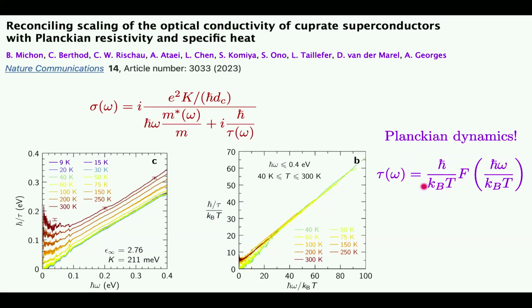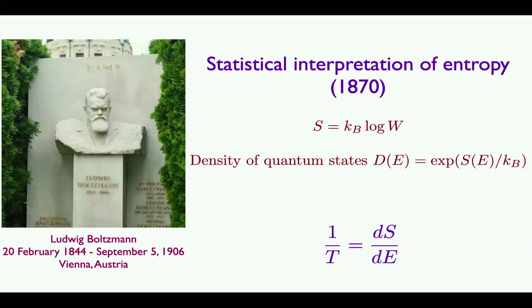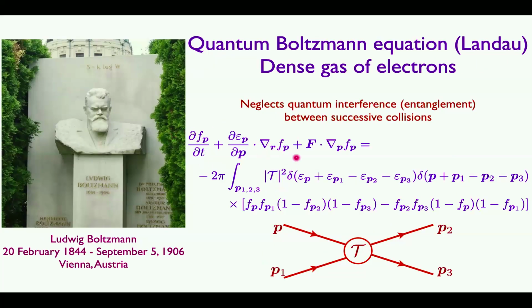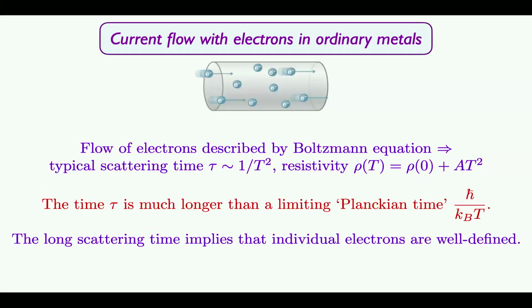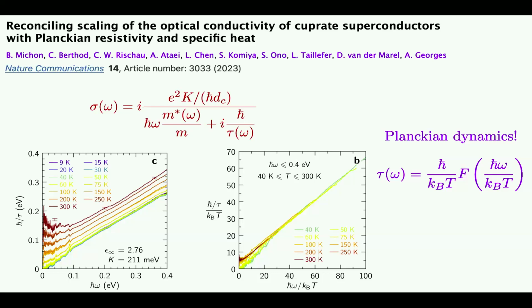And this is quite remarkable because the strength of the interaction, the fact that the repulsion, the Hubbard U, is about an electron volt, is not important at all. It doesn't come into the scattering time. Another thing that will never happen from Boltzmann's equation, because in Boltzmann's equation there is this T that I mentioned here, which depends on the strength of the interactions. Okay, so you get this universal tau of omega, which is just given by fundamental constants of nature, the frequency and temperature. So quite a remarkable behavior that you see in several compounds and in most detail studied in this particular material. I think this is lanthanum strontium copper oxide.